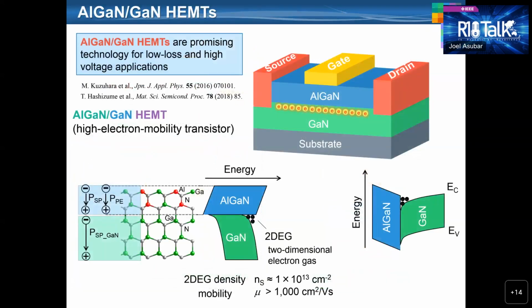Now, let me introduce the AlGaN/GaN HEMT, which is one of the widely studied GaN-based electron devices. Strong polarization fields in the AlGaN/GaN heterostructure result in a sheet of very mobile electrons which tend to gather along the AlGaN/GaN interface. This is called the two-dimensional electron gas, or simply 2DEG, which has a high density and mobility that can facilitate low resistance and high power operation.